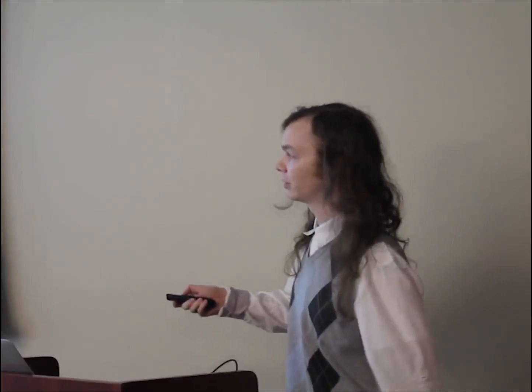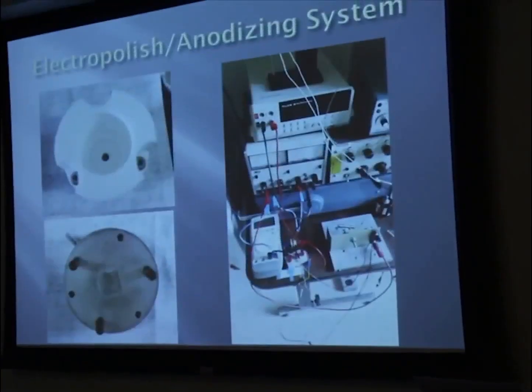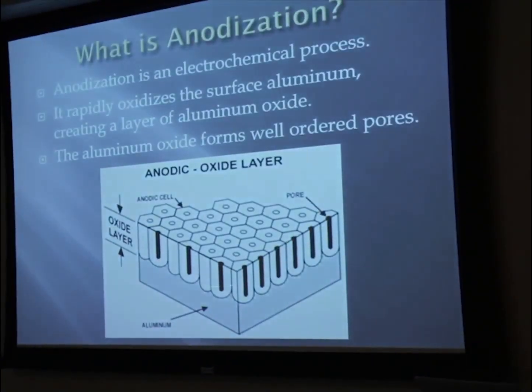Yeah. So the idea is we want to cause oxidation to occur on the surface of the aluminum rapidly. So that normally happens like for maybe like iron rusting. There's oxygen in the air, it naturally forms that rust layer. We're trying to create that to happen on the surface of the aluminum, but much more rapidly. So what we can do is fill this with oxalic acid. There's oxygen readily available. And by pushing a current through it, it causes that reaction to occur much faster, which allows that oxide layer to form and burrow in deeply.